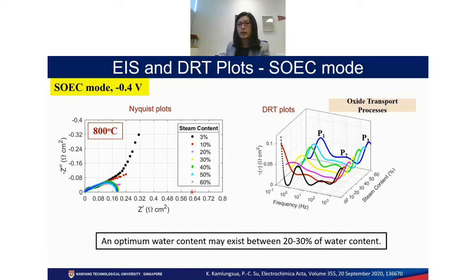Again, we look at this DRT plot. Okay, we see the first peak. So again, this black curve, the lowest moisture content, 3%, is high. And it dropped when it becomes 10% and slightly increased around this purple, hot pink, which is 20%. Then it increased again. So it also went through a drop and increase kind of behavior.